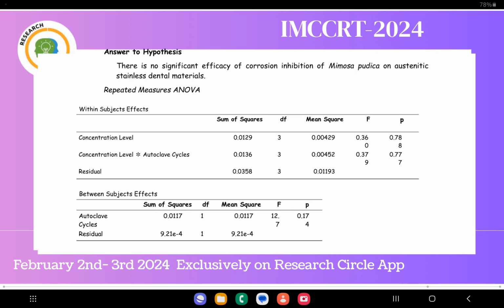Similarly, the interaction effect of concentration level and autoclave cycles yielded an F statistic of 0.379 with a p-value of 0.777, indicating no significant combined influence. The residual within subject effects, representing unexplained variance, were relatively small. Moving to between subjects effects, the autoclave cycles factor showed a trend, as indicated by an F statistic of 12.7 with a p-value of 0.174. However, this trend did not reach statistical significance at the 5% alpha level.